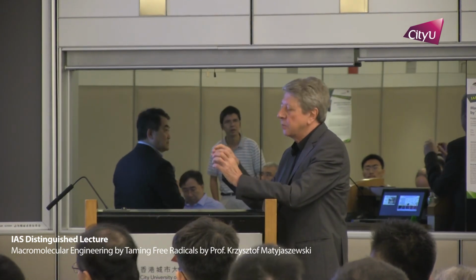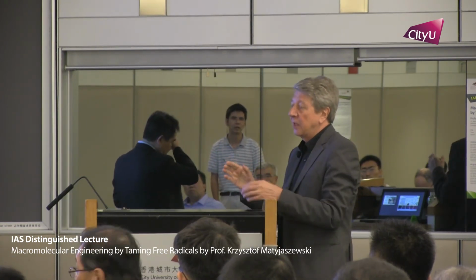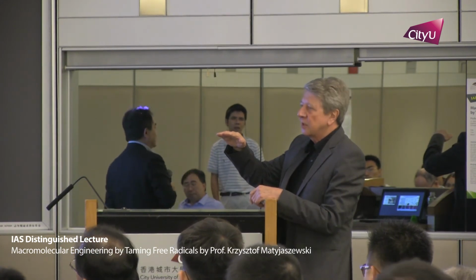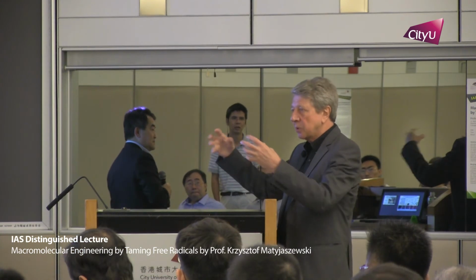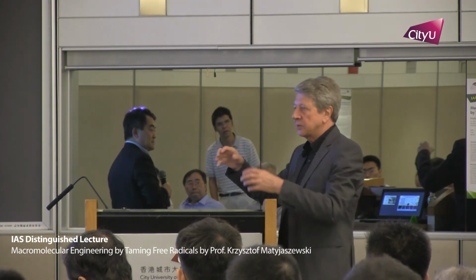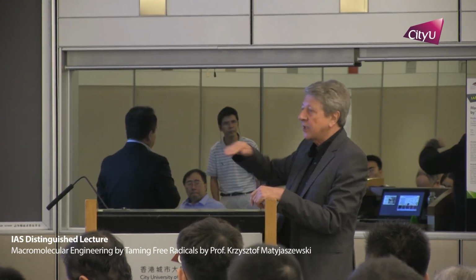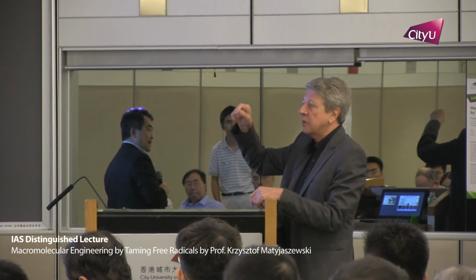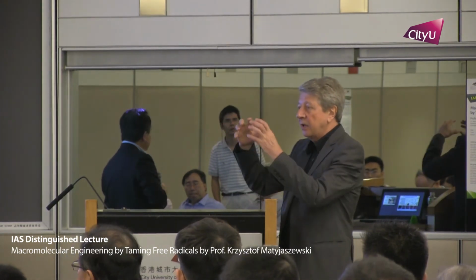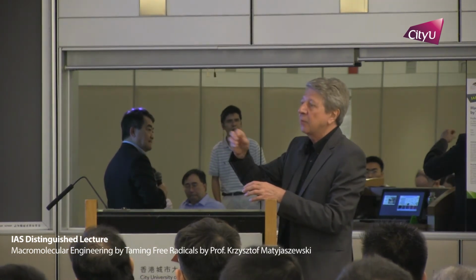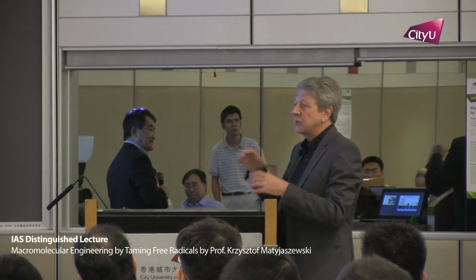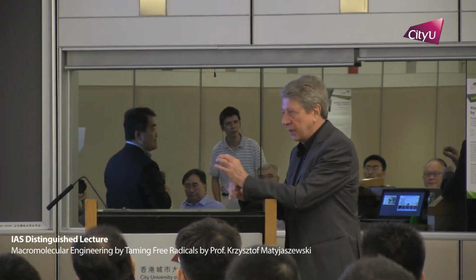We had one example of the barium titanate, which was grafted with polymer chains to disperse it better. And in fact, first, the effect was very poor because this catalyst could not approach the surface because of the highly grafted chains. But then if you continue sonication, it accelerates tremendously, probably because ultrasound can cleave some of these chains from the surface, make an open area, and then this catalyst can come, get reduced, and start the polymerization. So I think on one side it would be piezoelectric potential, and especially if you have a negative charge or excess of electrons on a surface, which can jump on a copper-2 species and then reduce copper-2 to copper-1.